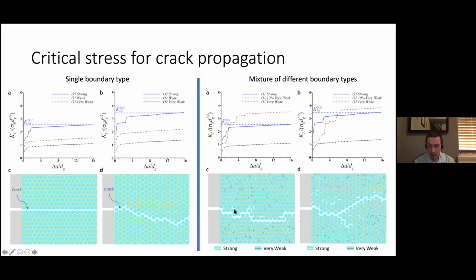And in fact, you see occasionally, for example, here and here, situations where a daughter crack is nucleated or where the crack branches into a different direction. It's even more pronounced in the case of orientation 2, which is what I have here on the right. In that case, it becomes even more difficult for the crack to make it from the left to the right without branching and without creating daughter cracks. So those sorts of phenomena are the direct impact of having a certain admixture of weak interfaces.